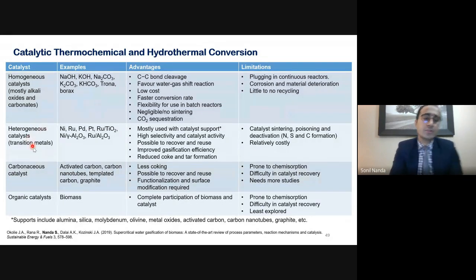On the other hand, heterogeneous catalysts are mostly transition metals, with examples mentioned here: nickel, ruthenium, platinum, palladium, and so on. The advantages are that they're mostly used on a catalyst support, and they have high selectivity and catalytic activity. There is a possibility to recover and reuse these catalysts because they are supported on different support materials, and the supported materials can be recovered easily afterwards. They can improve the gasification and pyrolysis efficiency, and they generally tend to reduce coke and tar formation.